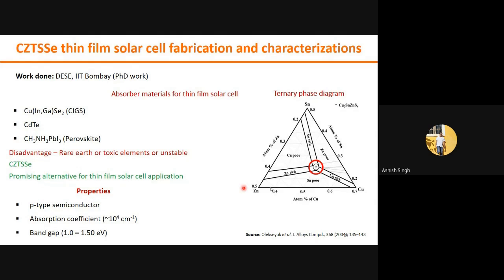If we see the phase diagram of CZTS, this is the window where we can get phase pure CZTS. If we deviate the atomic percentage of copper, zinc, and tin from this window, we will get CZTS along with impurity phases, and those impurity phases create recombination centers in the absorber and sometimes stunt the device efficiency also. So it's very hard to hit this point.